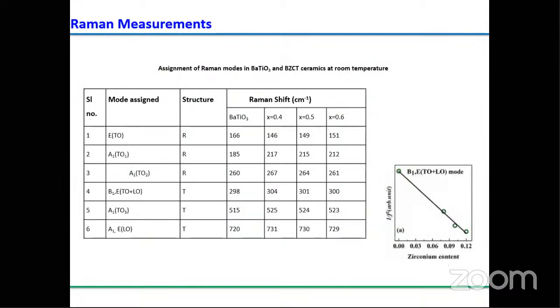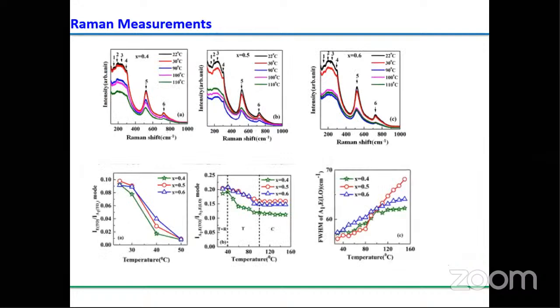These peaks 1, 2, 3 are shown at different frequencies, 166, 146, 149, 151. Units are centimeter inverse, which is what we call the Raman shift. Those peaks represent that our material has rhombohedral phase, and the other peaks around 304, 525 and 731, that is peaks 4, 5, 6, tell us the material has the tetragonal phase. So Raman measurements also told us these materials have the tetragonal as well as rhombohedral phase.